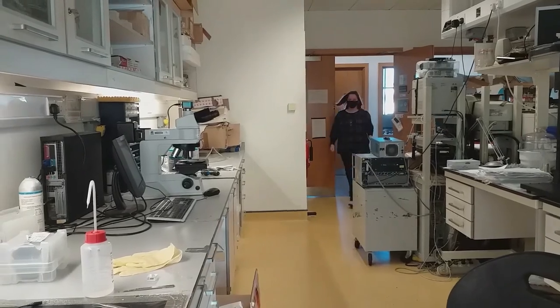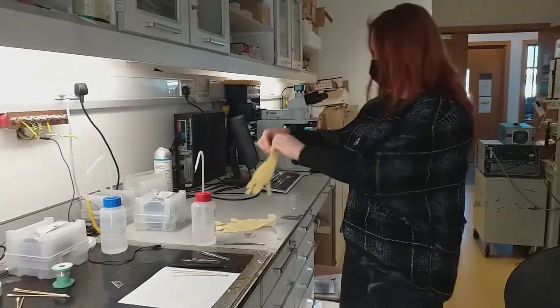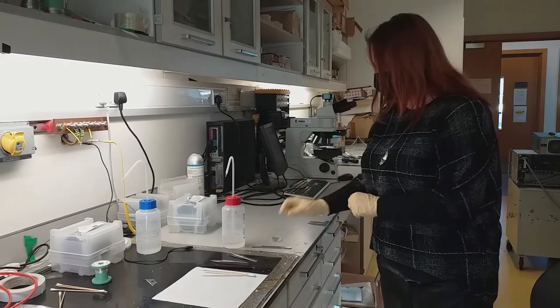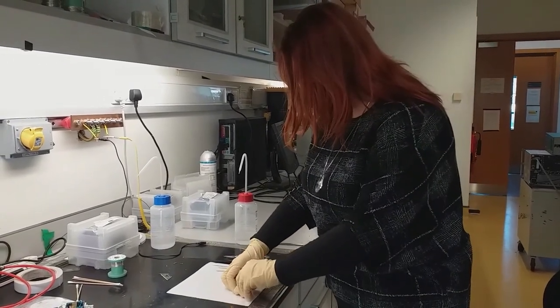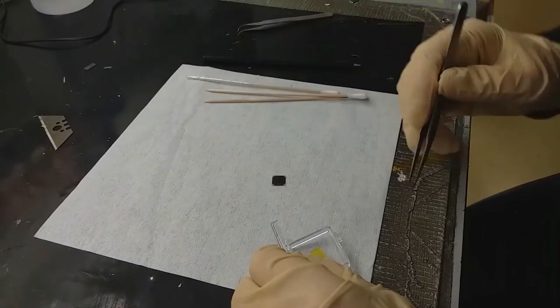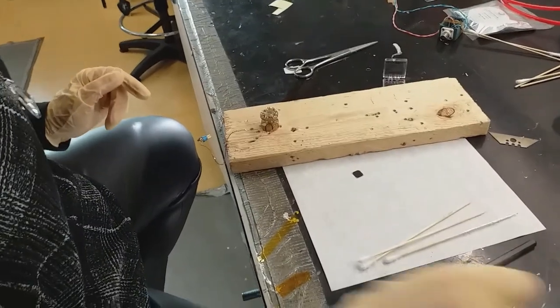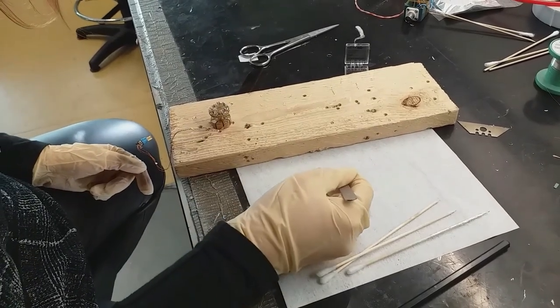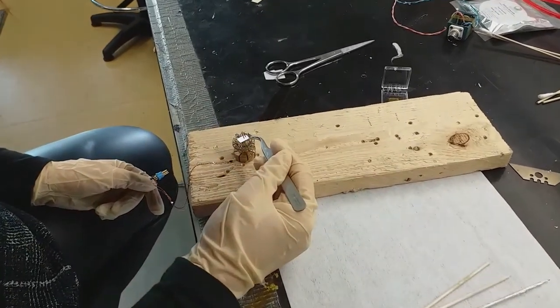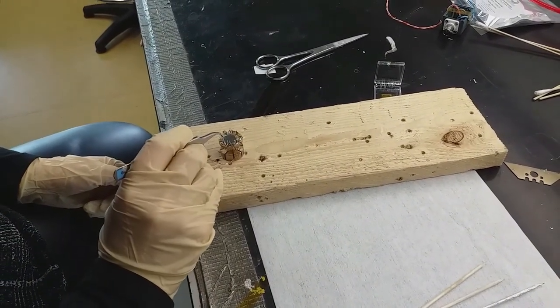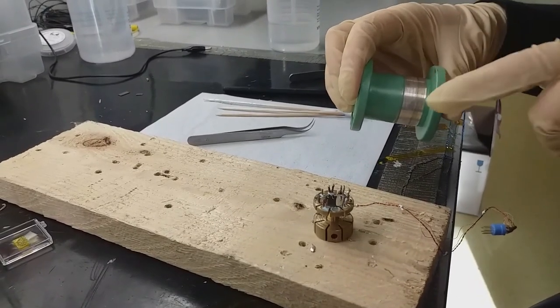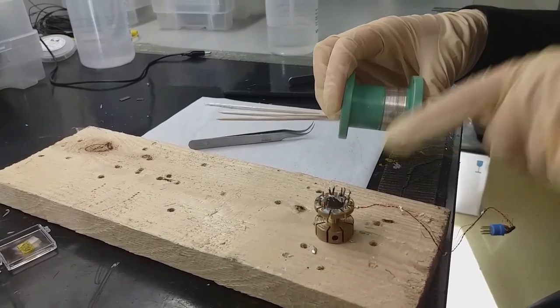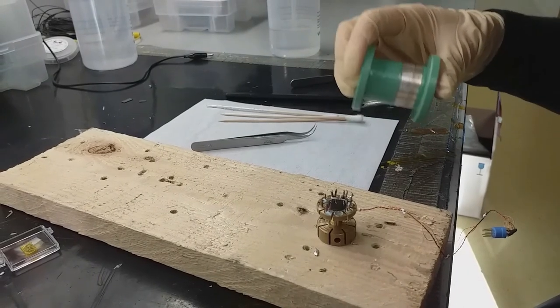My name is Katarzyna and I am a postdoc in the Magnetism and Spintronics group. I will demonstrate how to prepare a thin film sample for magnetotransport measurements in a cryostat with a superconducting cryomagnet. I've put gloves on and I placed the sample onto a clean piece of cleanroom tissue using tweezers. The sample holder for the cryostat is made of brass and it has some vacuum grease on top to allow the sample to stick to it. I placed the sample onto the vacuum grease and position it so that it's more or less in the middle. Then the thin silver wire shown on the spool is cut into pieces and using silver paint, a wire is attached to each corner of the square sample. The other end of the wire is soldered onto the correct pin.